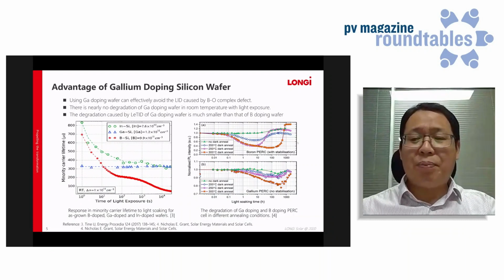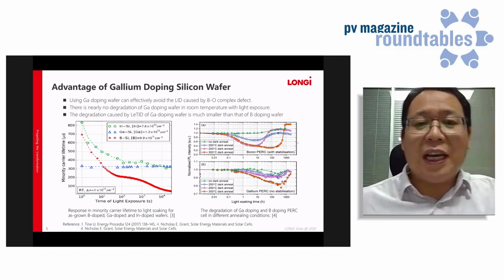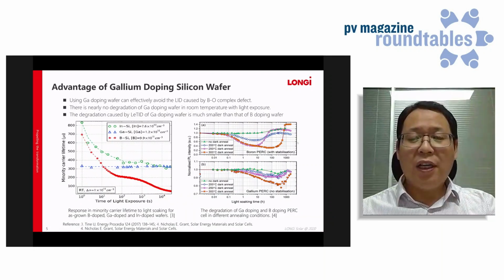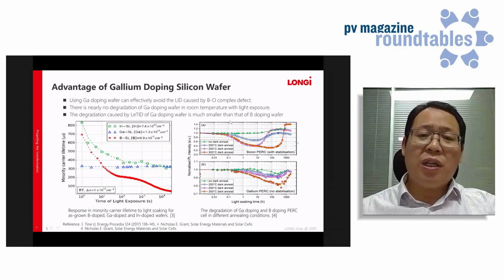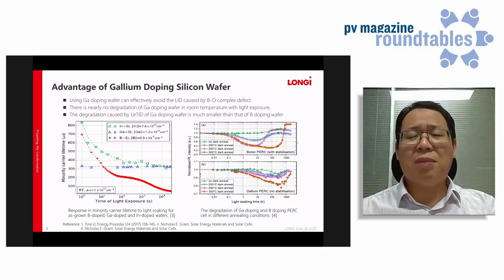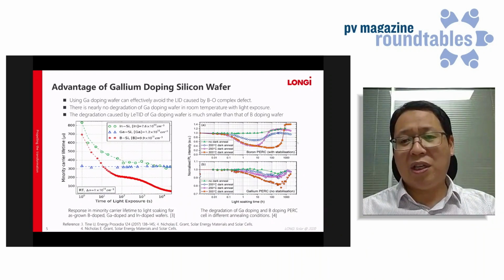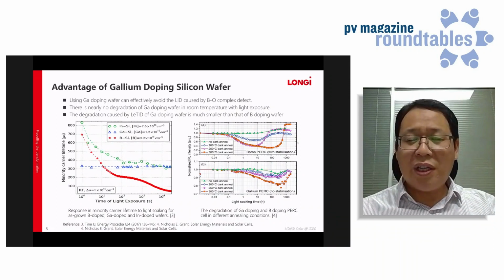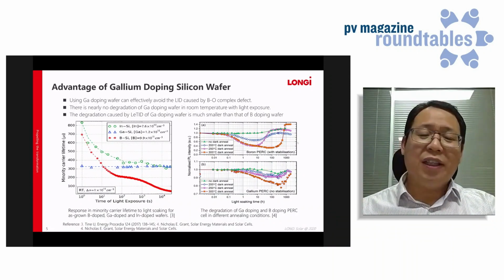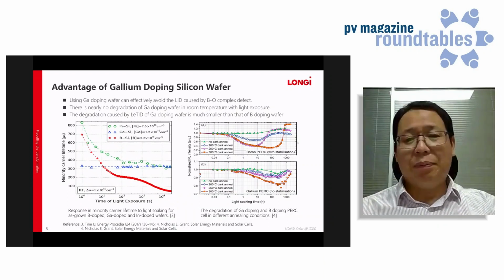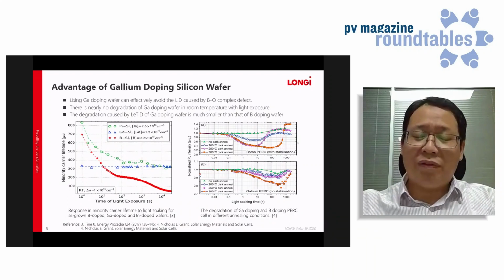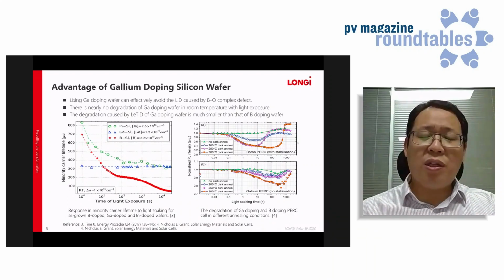We also made some tests comparing the LETID in gallium doping wafer and the boron doping wafer. The results show that by using gallium doping wafer, we get much lower LETID compared with the boron doping wafer. This is seen in the picture on the right side. You can see the degradation rate, and the degradation is lower if we use gallium doped wafer compared with the boron doped wafer. So we can conclude that by using gallium doping wafer, we can not only inhibit the LID, but also the LETID can be quite reduced.